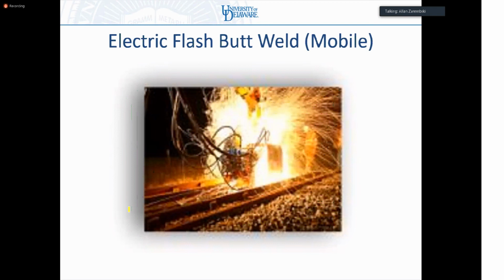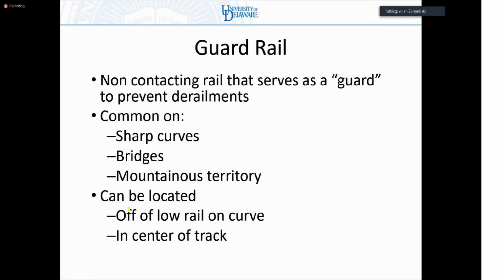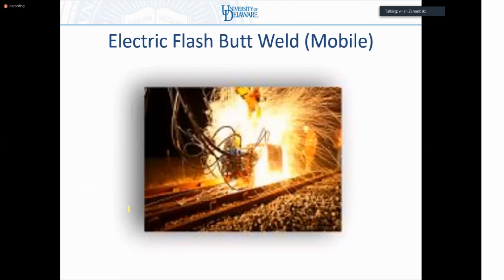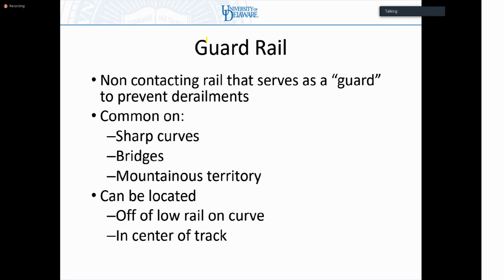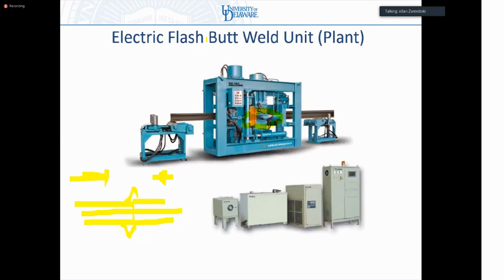So in order of strength, the thermite weld is the weakest. The electric flash butt weld is stronger than a thermite weld, but not quite as strong as parent rail. So pure rail. So that's why I want to roll my rail as long as possible, because rail itself is stronger than any welded joint process. But of the two welding processes, the electric flash butt weld process produces a stronger weld, a significantly stronger weld than the thermite process. But it's more difficult to apply.